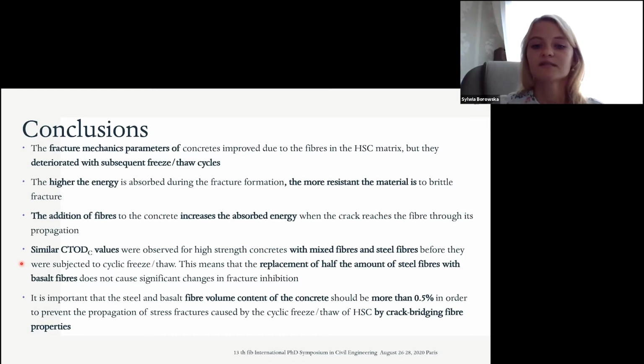The decrease in the mechanical properties of concretes with fibers was also caused by a decrease in the adhesion of the basalt fibers to concrete due to the loss of the continuity of the fiber's outer coating. Freeze-thaw cycling in the initial phase contributes to the increase of fracture energy. However, as the frost degradation process progresses, the fracture mechanics parameters deteriorate. The increased absorbability of high-strength concrete with fibers resulting from porous regions leads to a concentration of tensile stress in these areas as a result of freeze-thaw cycling, and as a consequence to internal degradation of the concrete.